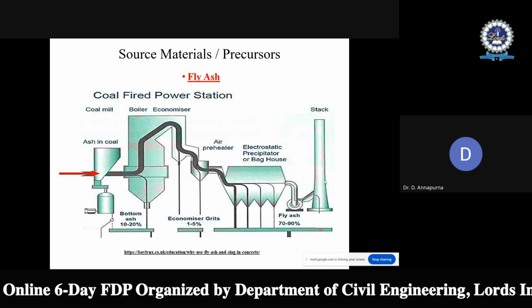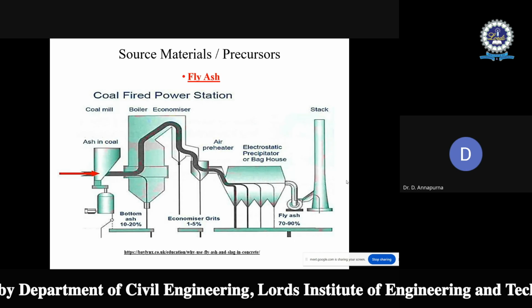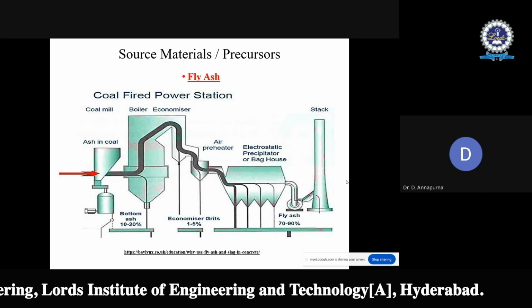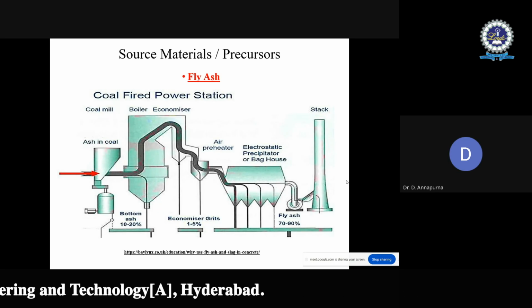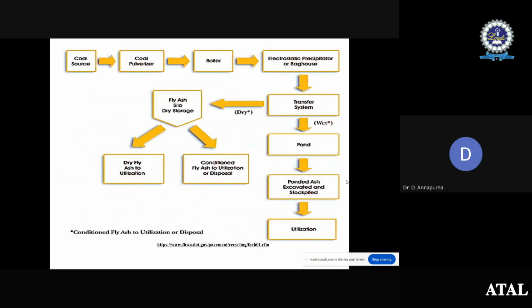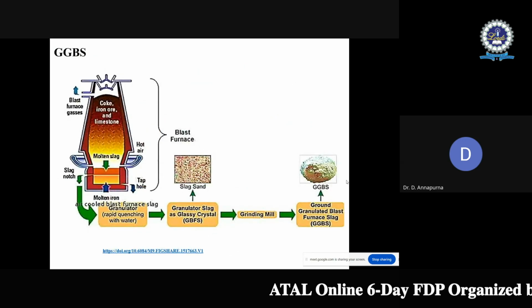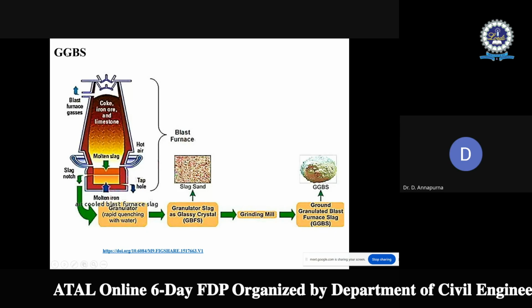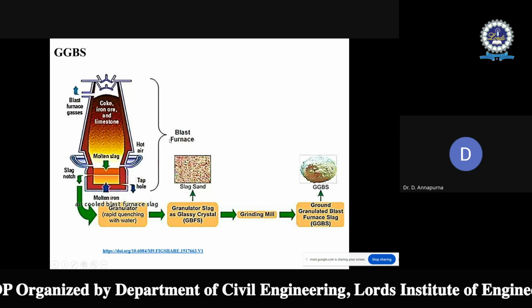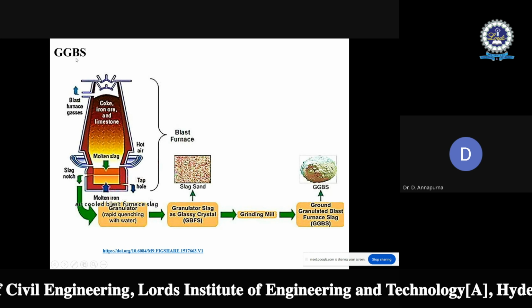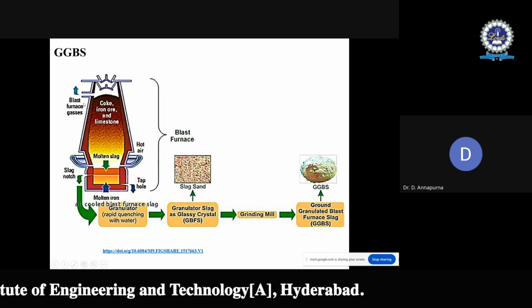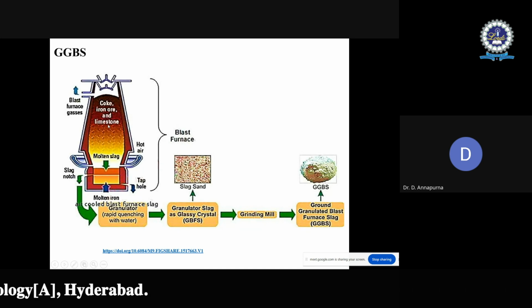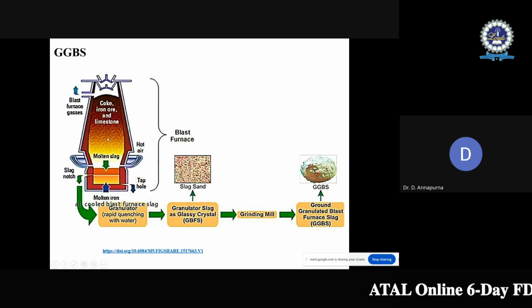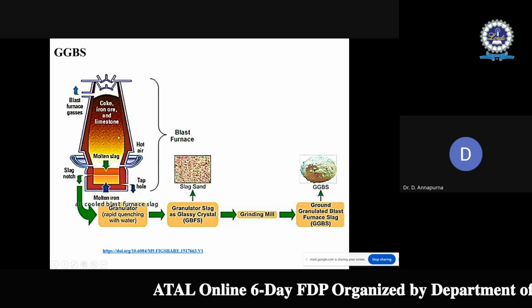This fly ash is rich in silica and alumina, so it is a perfect pozzolanic material. It can be used as a supplementary cementitious material and as a source material in the production of geopolymer concrete. The next one is GGBS. GGBS is also called ground granulated blast furnace slag because it is produced from blast furnaces. It is a byproduct from the blast furnaces used to make iron. These operate at a temperature of about 1500 degrees Celsius.